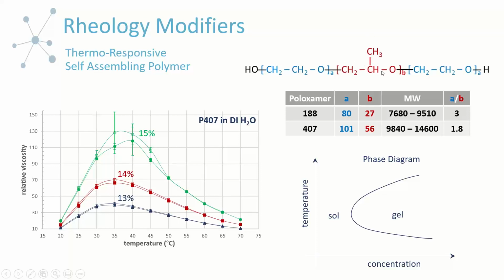So when we put this in water or some buffer type formulation, and again, this will be sensitive to things such as pH and ionic strength, now we have the ability for this to self-assemble because we have blocks that are more hydrophilic, blocks that are more hydrophobic. And the nature of the hydrophobicity and therefore the nature of the self-assembly is highly sensitive to temperature. Because one of the things that changes in these aqueous systems with temperature is the extent of hydrogen bonding, because of the thermal motion and whether it's faster or slower depending on temperature.